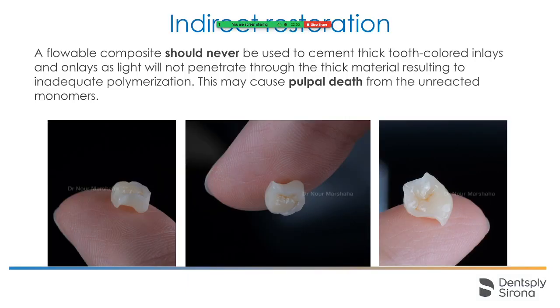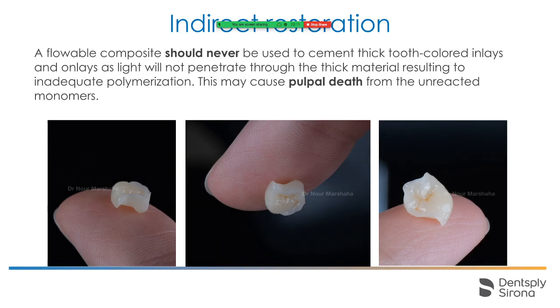A flowable composite should never be used to cement thick tooth-colored inlays and onlays, as light will not penetrate through the thick materials, resulting in inadequate polymerization. This may cause pulpal death from the unreacted monomers. Please notice and memorize this point.